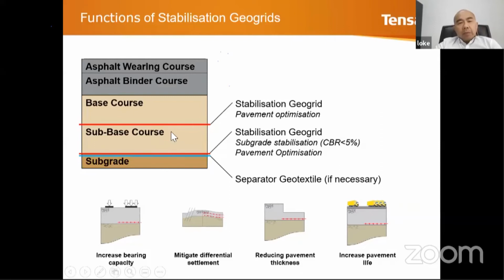Now, by putting a layer of geogrid, as we know already, it helps us to increase the bearing capacity. So you can see that you can put more loading here compared with the section without geogrids. We can mitigate differential settlement. You can see with the layer of geogrid, the settlement is even, and here you have the highly differential settlement. We can reduce the pavement thickness. You can see with the layer of geogrid, the pavement thickness is much lower, saving cost, saving construction time, and also reducing carbon footprint.